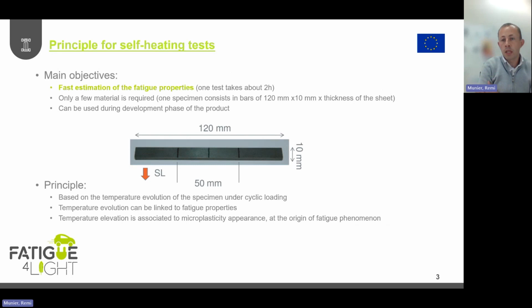For the principle of the test, as Sergi and Lucia said, the objective is to have a fast estimation of the fatigue properties. One self-heating test takes about 2 hours for one specimen. We need a reduced quantity of material. Here you can see the geometry of the sample, and it is very interesting in terms of product development. Then the idea is to measure during the test the temperature evolution of the specimen under cyclic loading, just as Stromeyer did more than 1 century ago. And then the idea is to directly link this temperature evolution to the fatigue properties.